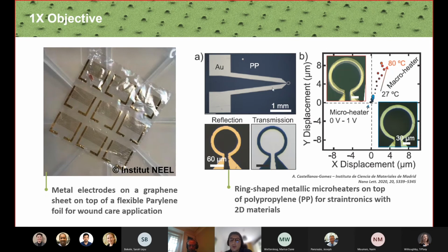Another example is also on a flexible substrate. Here you have a ring-shaped metallic micro heater, which has been fabricated on top of a polypropylene foil. These are used typically for straintronics with 2D materials. Our customers make this micro heater, then transfer 2D materials into the middle of it, and then look at the optical properties when stretching the material by locally increasing the temperature of the polypropylene with this micro heater.